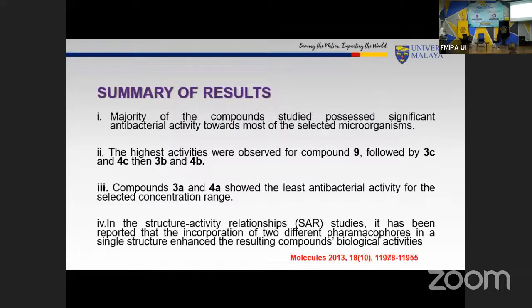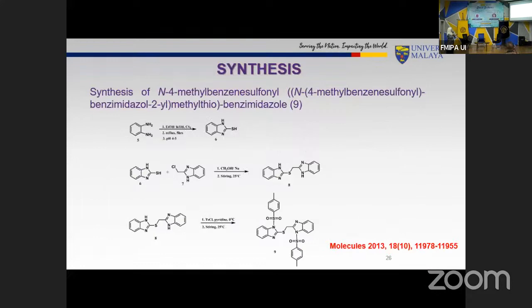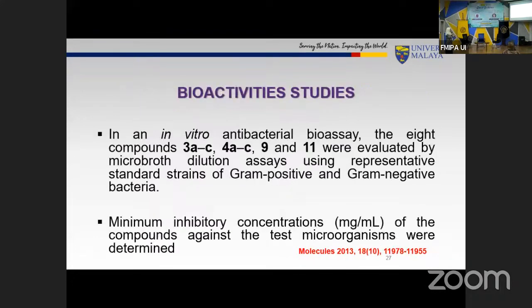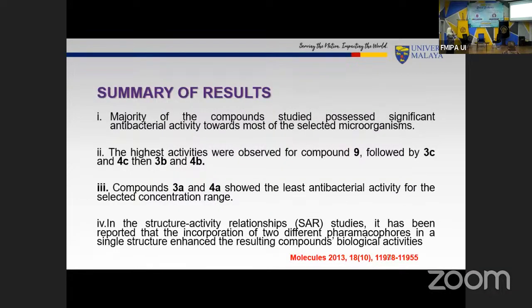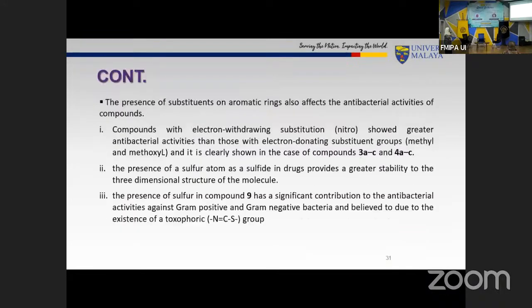So summary of the results, majority of the compounds studied possess significant antibacterial activity towards selected microorganism. The highest activity observed by compound 9. So which one is compound 9? Down there, compound 9. Okay. In the structure activity relationship SAR study, it has been reported that incorporation of 2 different pharmacophores in the single molecule enhance the resulting compounds biological activities. And the presence of substituent on the aromatic ring also affects the antibacterial activities, for example, one compound with electron withdrawing substituent, that is nitro in this case, showed a greater antibacterial activity than those with electron donating substituents.